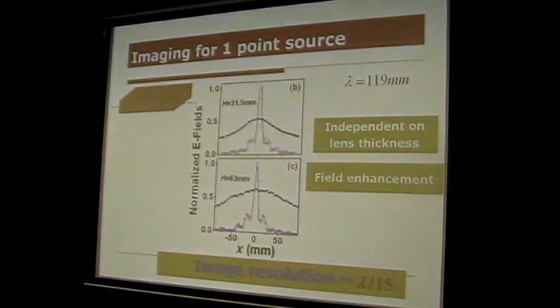Indeed, if we put an antenna here and put another antenna along this direction on the other side of this lens to measure the field distribution, you'll find that without the lens, the field distribution is very broad, without any resolution. However, if you add our fractal lens here, you find that the field distribution is very sharp, and it also has a very good resolution. If you look at the wavelengths, you'll find that the image resolution is about lambda over 15, which is very subwavelength. And also the field is strongly enhanced if we add the fractal lens here. We then performed the FDTD simulation. We found a perfect agreement between the FDTD simulation and the microwave experiment.